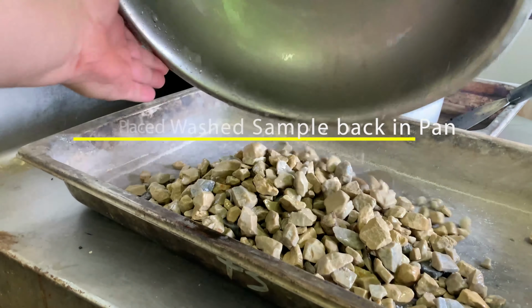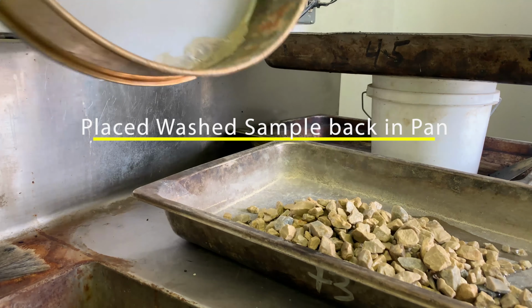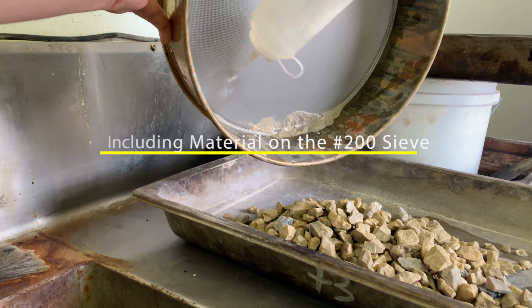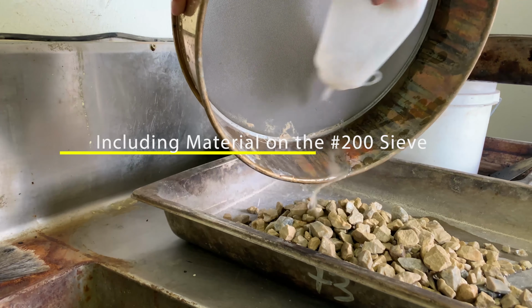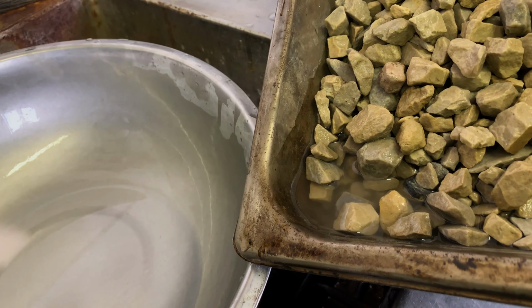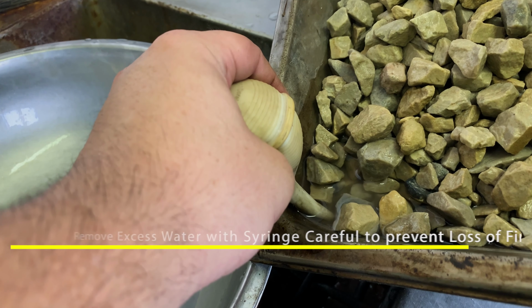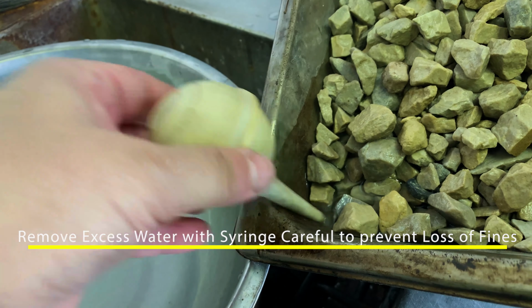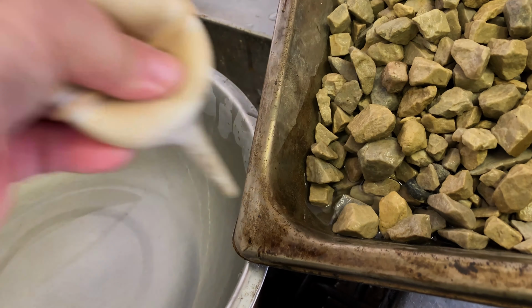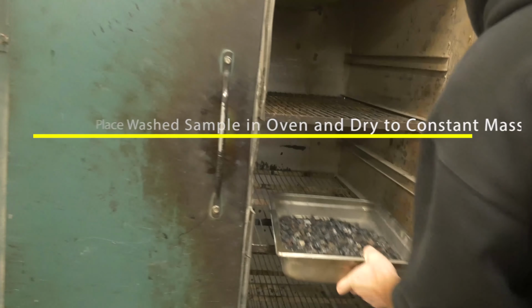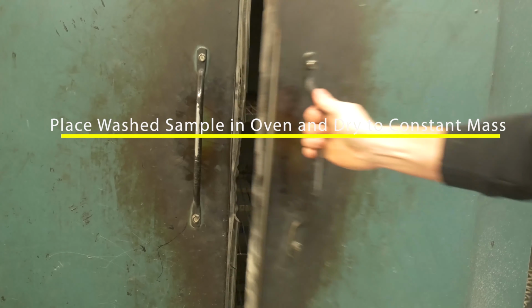Once clear, place the washed sample back into the pan, including the material left on the number 200 sieve. Remove excess water with a syringe, careful to prevent the loss of fines from the sample. Place the washed sample in the oven and dry to a constant mass.